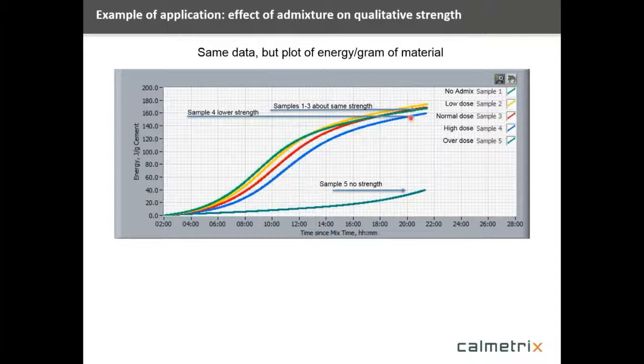So this is a graphical example of how you can use the power of what we can get from the isothermal devices to look at the data in various ways and maybe come to a different conclusion compared to just looking at the set time data. And graphically, you can tell here that sample 5 does not develop any strength at all, really, compared to the other 4 samples. So again, a very powerful, simple example of how the instruments can be used. The first curve, with the power curves, could be done with either the isothermal devices or the semi-adiabatic, but in this case, this is really only appropriate with the isothermal devices.